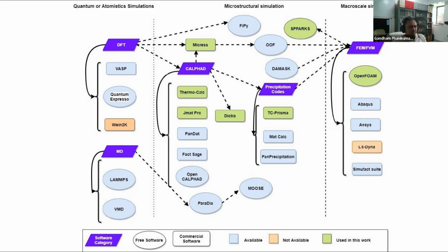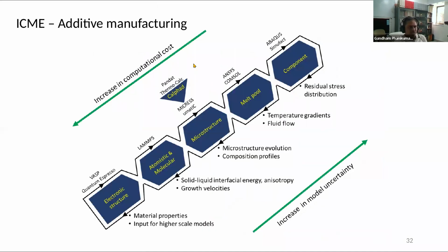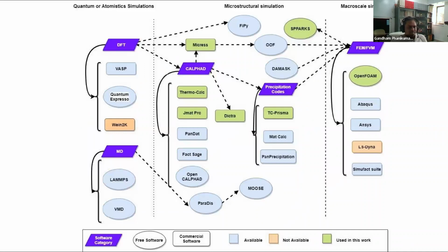So today we can actually do the computational optimization before we go to the printer, so that in 1 or 2 iterations, we get the best component from the printing. In fact, we have demonstrated it already by making a very good component in the very first iteration when we worked with Professor Keshavan's group on Haynes 282 alloy, and we have already submitted one manuscript for that recently. So today we have this ICME approach that is possible, an integrated approach to combine all the scales from the component to the microstructure and down to whatever is happening at the atomic and molecular scale also. And therefore we can actually build defect-free components by understanding thoroughly.